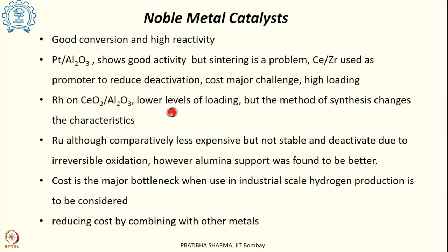It is found that how the catalyst is synthesized has an effect on the entire process. Like if the catalyst is synthesized using low temperature methods such as wet impregnation, in that case they work well under the lowered operating conditions. However, at higher operating conditions they are prone to more sintering.